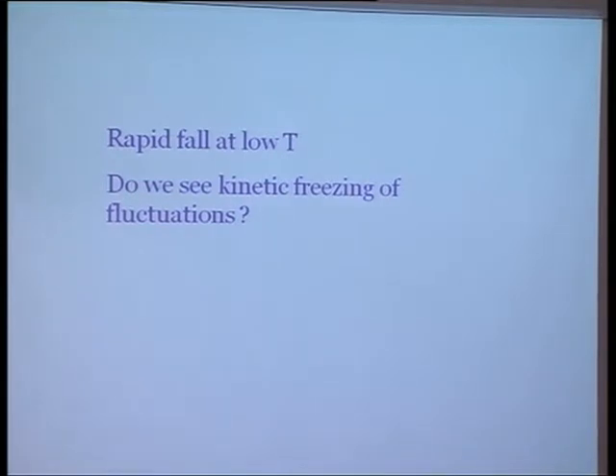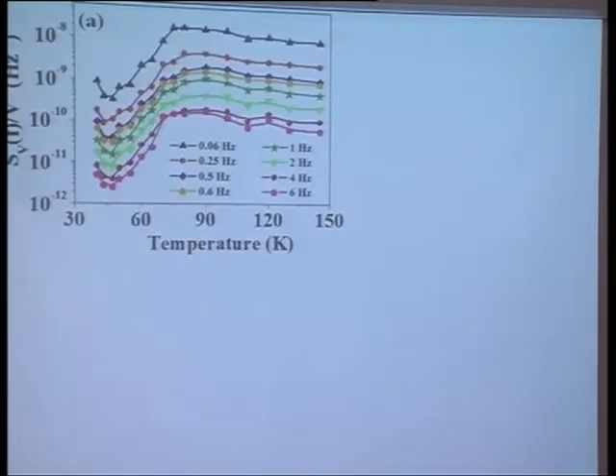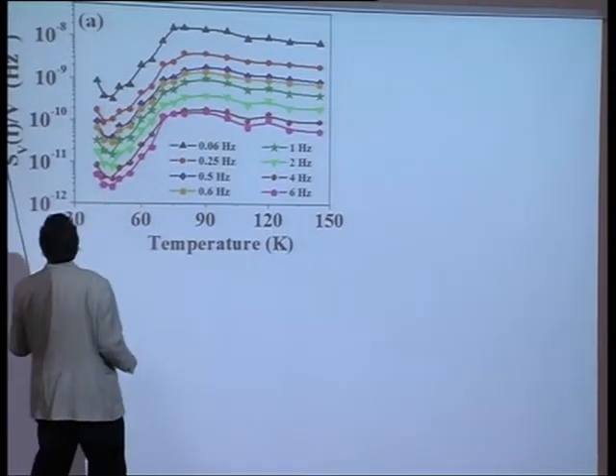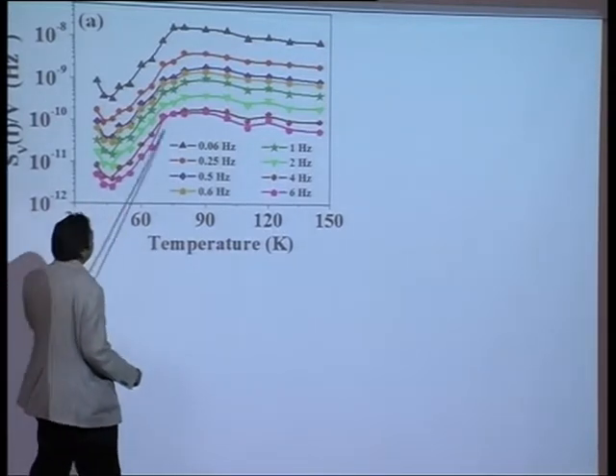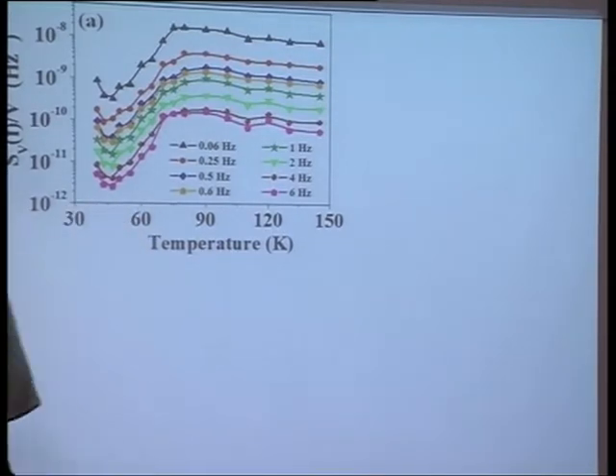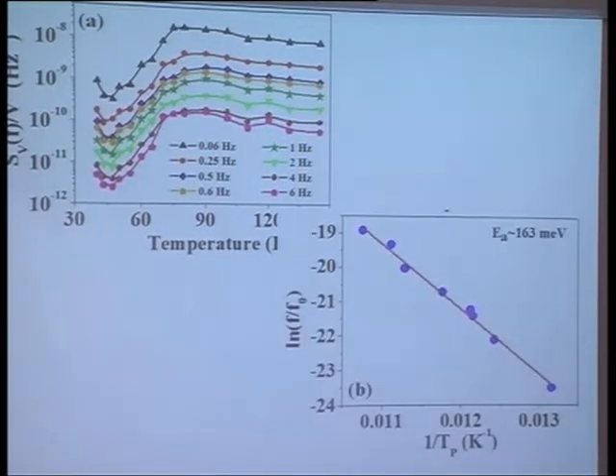So our question is, do you see a kinetic freezing, where the fluctuations have a much longer time scale than our scale of measurement? So how do we do that? We measure this quantity, the spectral noise, at different frequencies, spanning about two orders of magnitude, as a function of temperature. It's a very limited temperature and frequency range that you get, but you do see an activation over there.